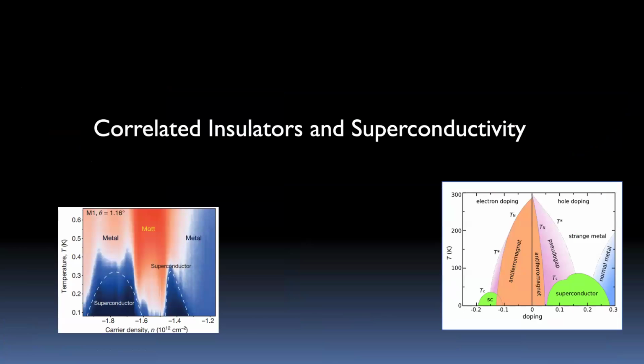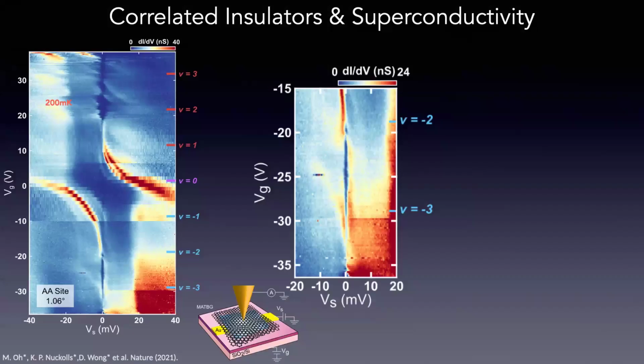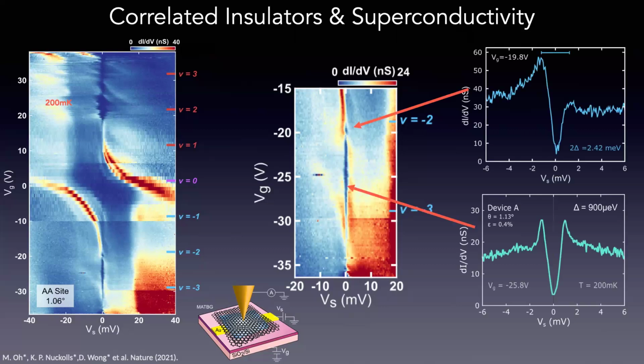Okay, so now with that introduction of the normal state, let's cool the system down and ask what kind of insulating state and superconducting state we find. As you cool it down to millikelvin, this is 200 millikelvin, you start to see features. Those cascade features go away at very low temperature, and they're replaced by particular fillings, with very sharp gaps. This particular one is at half filling of the valence band, so you have 2 electrons per moiré unit cell inside the lower band, and you see a very sharp gap. And this gap opens and closes, and then another gap opens between -2 and -3.